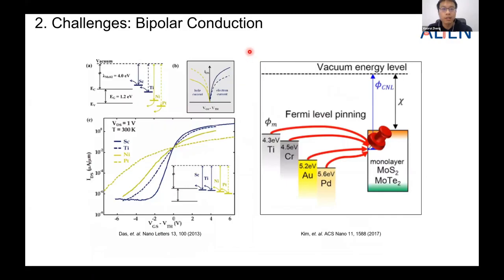The second challenge we are facing now is, in theory, if we can tune the work function of the metal contact by choosing different metals, like a low work function metal, we would have N-type conduction. If we choose a large work function metal, we would have P-type conduction. However, in reality, no matter what metals we use, the Fermi level is pinned to a certain level. So we cannot observe the bipolar conduction for certain materials like MoS2. So this is the second challenge.